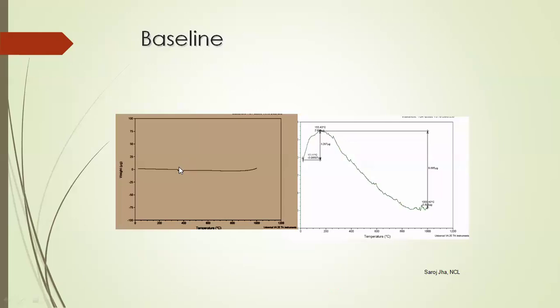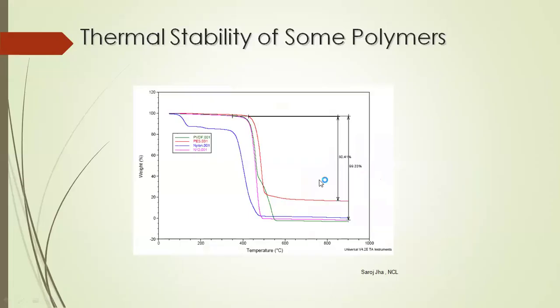Second thing is your baseline. What is baseline? Baseline is heating your sample holder without your sample up to the temperature range of your interest. And your baseline should not have deviation or any sample degradation or any step in the degradation. Why is this? Because a previous user might have left some residue or have some sample spillage on your heater, or some sample is oxidized and attached to the corners of your sample pan. That can happen, and that will always play into your real sample behavior. Maximum you can have around 0.005 milligram of weight change in your TGA. This we have already seen, so I will not spend much time on this now.